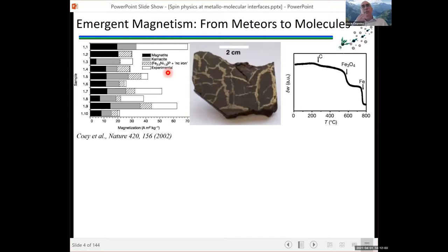When you try to measure magnetic carbon in a sample that already has iron and iron-nickel compounds, this is not trivial, and there is always a lot of risk of misinterpreting what you are seeing. But they were quite confident that the magnetism of the sample was not only due to the iron and the iron-nickel compounds in the sample, but that at least some 20 to 50%, depending on which sample they were analyzing, was due to this magnetic carbon, where the spin order was induced by the other metallic compounds, and where the high pressure and high temperatures that occur when a meteorite hits Earth somehow form this pyrolytic magnetic carbon. In thermogravimetric analysis, they attribute a change, a Curie temperature of about 200 degrees C, to this carbon, where the other steps could be attributed to conventional materials like magnetite or metallic iron.